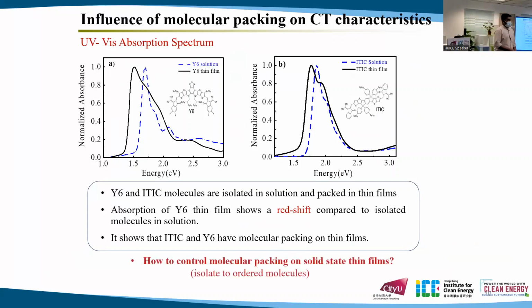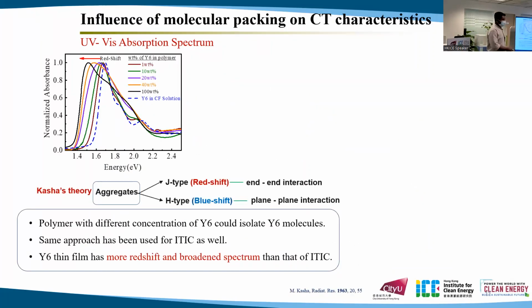Then there is a question: how can we control the molecular packing in solid state thin films, how can we disperse these molecules? That was the main challenge for us. And we used the dilution effect. We used a polymer in order to disperse Y6 in the polymer matrix. And you can see that when we increase the concentration of Y6 in the polymer matrix, there is a gradual redshift.